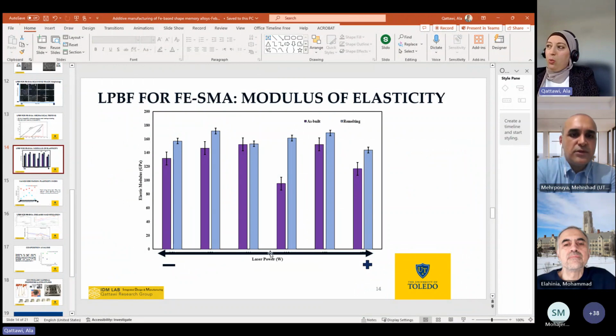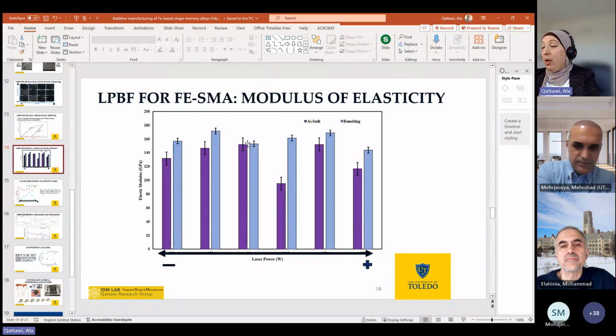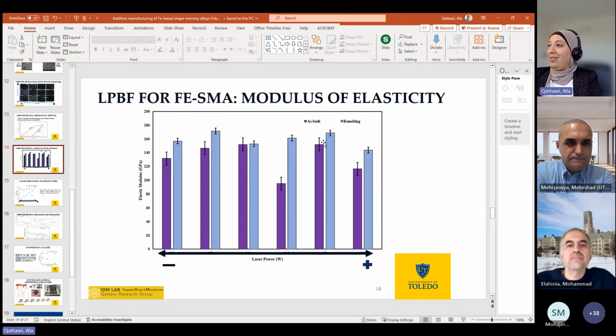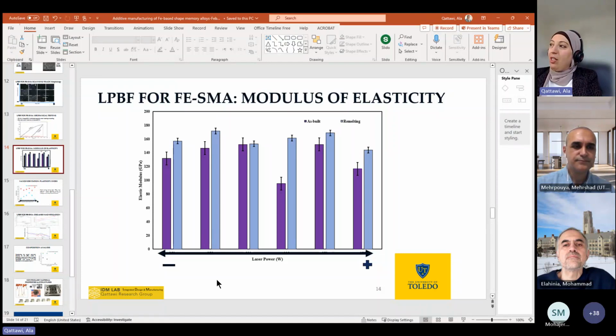So this is a good question. When we look at the as-built one, the dark purple one, you can see that it's not like a line. So sometimes you have an increase in laser power, and then significantly after that, the material behaves better, right? So in laser powder bed fusion, it's not like a line, where whenever you increase the laser power the material properties simply increase or decrease. Usually what we find is that because of the thermal dynamics of the melt pool, that will affect what happens afterward for the mechanical properties.